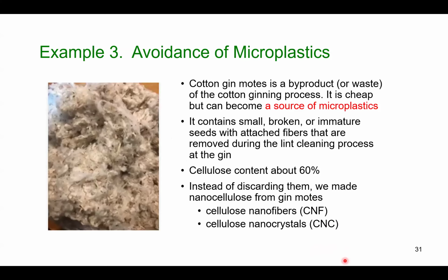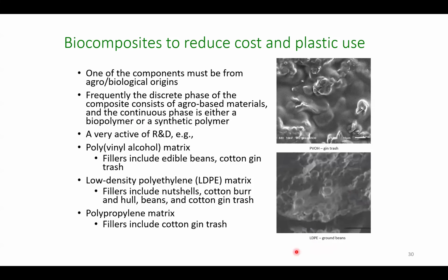So the key thing here is that as long as the performance holds up for the application in question, we can use the fillers to reduce the cost, and therefore also reduce the plastic use. So we can use filler as much as 40% in order to reduce the plastic. So we still have the benefit of the plastic, but reduce the use by using bio-based, agro-based fillers.